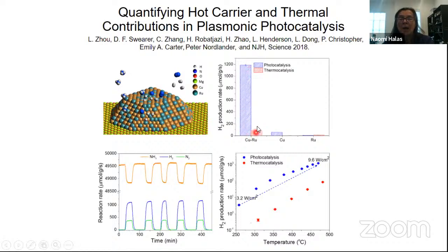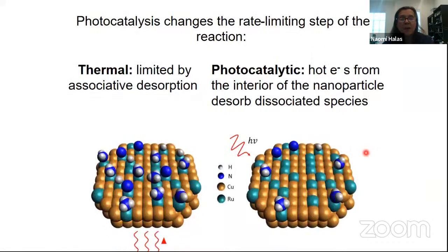Okay, so light on, light off, a very huge difference. And you can see the reaction rate here. You can see the components, both the hydrogen and nitrogen and so on. Comparing photocatalysis to thermocatalysis, this is a far more efficient process, and here we're just measuring, of course, the hydrogen yield when we decompose the ammonia molecules. So you see they're very different, and the mechanisms are quite different. So what is happening in this? What we're actually doing, as I'll show you in a moment, is we've changed the reaction order, and we've actually changed the rate limiting step of the reaction.